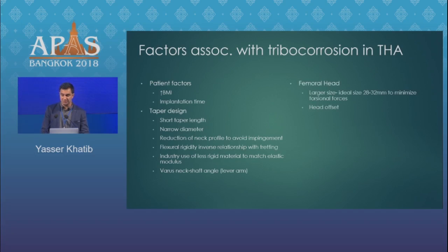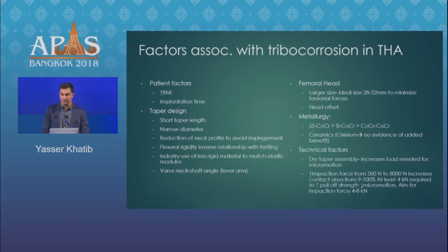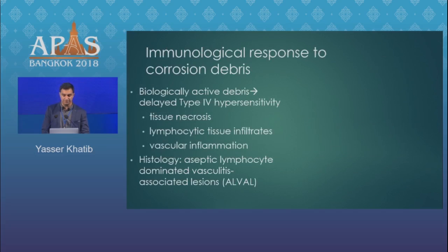Femoral head size seems to play a major component, and offset also seems to have a component. We talked about metallurgy. Ceramics seem to be more protective, however, Oxinium doesn't seem to have any added effect. And the way you impact the taper is important. You need a dry environment to impact it to increase your contact areas, and you have to give it a fair whack. 4 kilonewtons is the minimum recommended there.